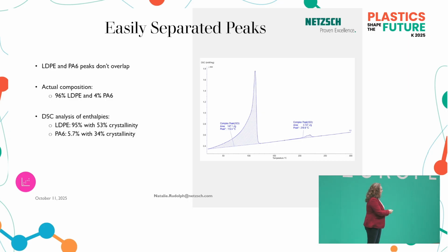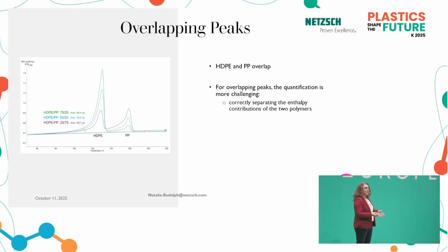Here you see an example of LDPE, maybe with a nylon 6 barrier layer. Super easy to distinguish because LDPE is this peak, nylon 6 is this peak, very far away. We can easily distinguish between the two. The actual composition was 96 and 4%, and with the DSC analysis and knowing enthalpies, we got very close to that.